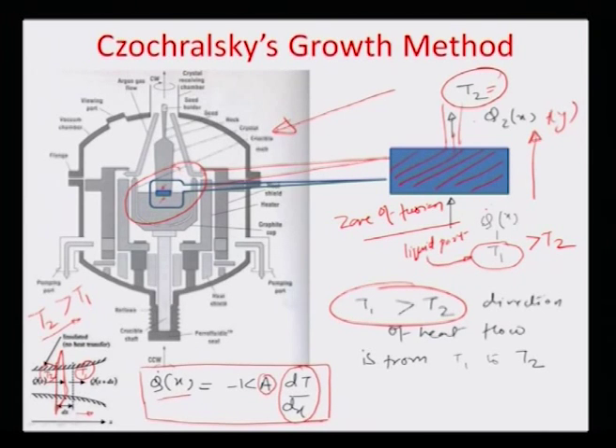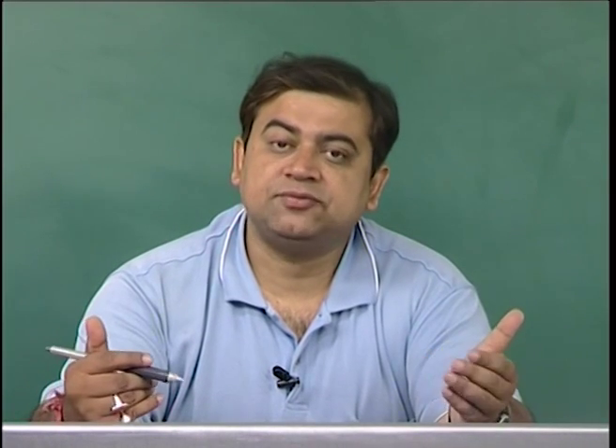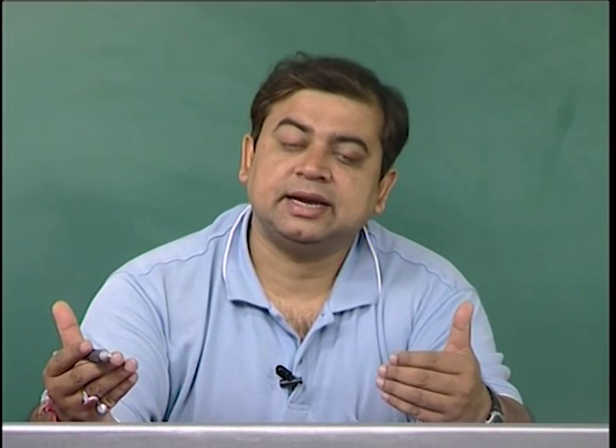is also a cause of the formation of the solid, which means that in a solid state, as you know, the bond energy is always higher, and therefore there is a heat of formation of the solid which is lost. It's called the latent heat of formation of the solid. So the difference between the rate of heat flow into the zone of fusion and out of the zone of fusion is really the quantity of heat which is lost in formulating the solid from the liquid state.